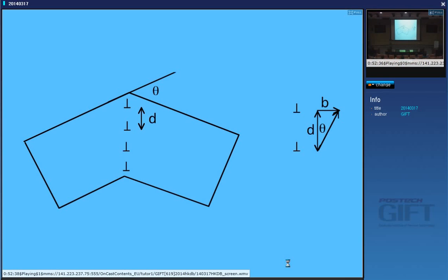And the spacing between the dislocations depends on the Burgers vector of the dislocation and the amount of tilt between this side and this side. Okay. So if I increase the angle theta more, then the spacing will decrease because I need to fill that hole even more if theta is large, right? So the structure of an interface can be described in terms of a series of dislocations, the spacing of which depends on the Burgers vector of the dislocation and the angle theta.